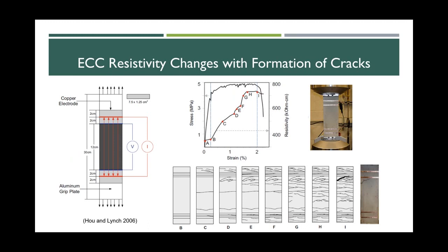And by doing so, because of the crack formation, ECC's resistivity or conductivity, the electrical properties, change. And such change you can see from here: from no cracks, the no-crack A and B, with very few cracks, it basically has very, very low resistivity. And once you have more cracks, the resistivity goes up. So that's how you understand.